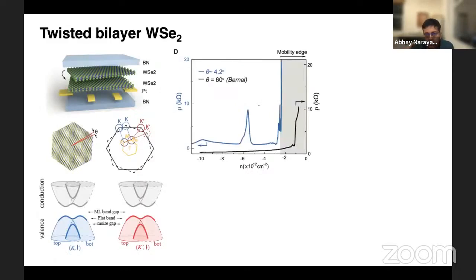So here are some transport data on one of these samples. What's shown here is the resistance as a function of filling. Here is the edge of the valence band, and going in this direction you're filling holes into the valence band. I'm showing you this blue curve, which is taken for a sample which has a twist angle of 4.2 degrees, so it has a superlattice. And then this black curve is for a sample that has a twist angle of 60 degrees, which is the natural form in which this material occurs, the Bernal stacking. You see that this black curve differs from this blue curve in that at a particular value of the density, this blue curve shows a peak. And this peak corresponds to an insulating state.